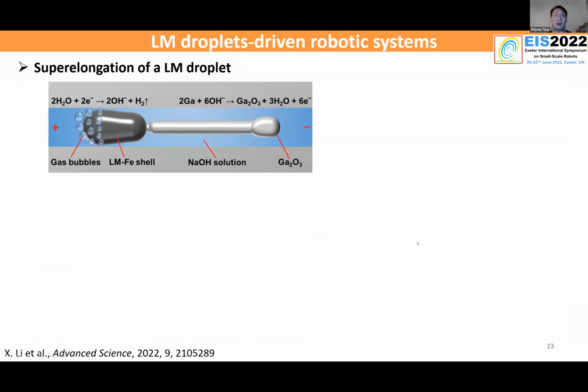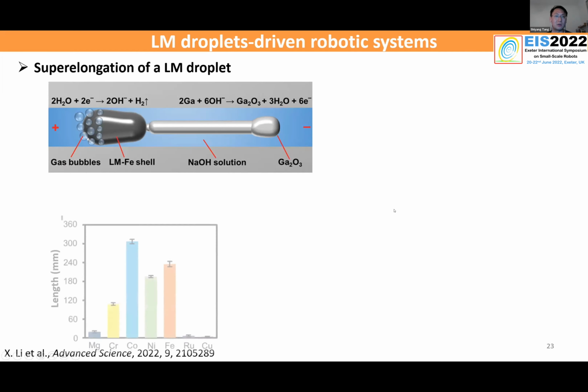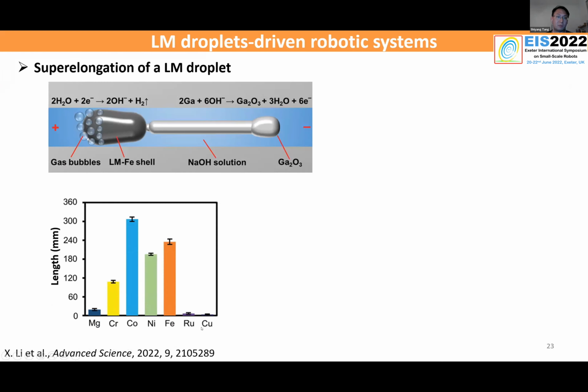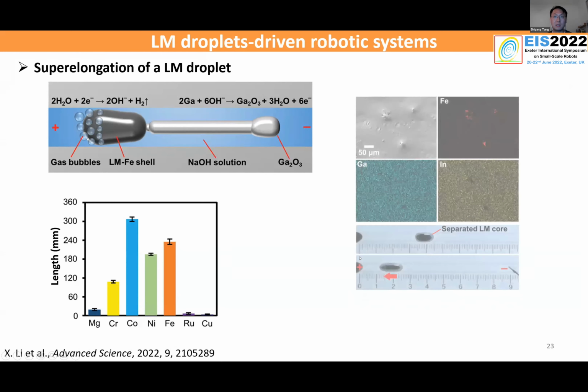We're trying to borrow a similar idea, and the principle is relatively simple and straightforward. It's basically just oxidizing one side of the liquid metal, so it's able to elongate and be driven towards the cathode. We tried doping with different particles, and it seems that particles with a higher standard electrical potential than gallium work.